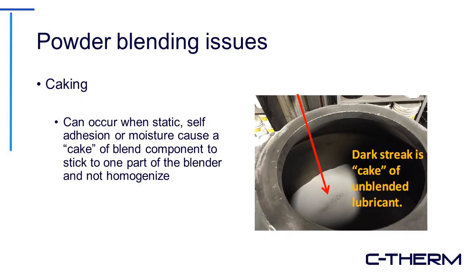Another common cause of powder blending problems is caking. So this can occur when static powder self-adhesion or when moisture cause a cake of material to stick to one part of the blender and not go into the full blend. So in this case, you can see an image, a dark cake of the unblended lubricant, which was actually stuck to the top of this blender, and it fell off the top onto the powder blend when the lid was open to take this photo. So that's an example of what caking looks like in practical terms.